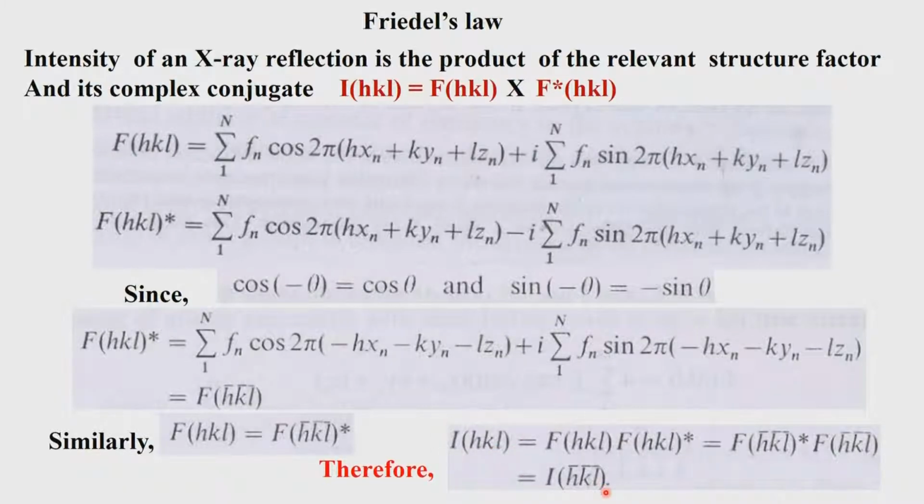But when you actually do this exercise with a compound where you have a very heavy element and it is going into a non-centrosymmetric system, it is possible that the system which is now generated may show I of HKL as not equal to I of H bar, K bar, L bar. So, what was in my example 10,000 may become 4,600. There is a huge difference between these two. It cannot be mainly due to the absorption or the size of the crystal, it is due to some other effect. That other effect is known as anomalous dispersion.